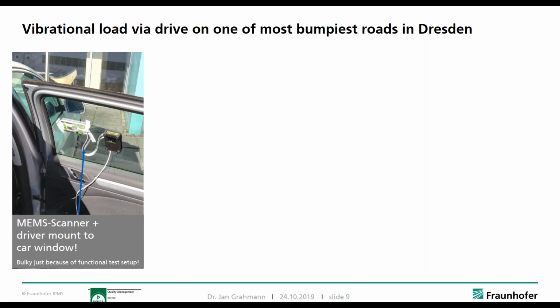For the resonant axis, that's different. For a resonant scanner, you basically have an approximately sinusoidal motion, which you cannot compensate. Each sinusoidal trajectory has a certain linear part, but it is of course smaller than what we can do with a quasi-static scanner. If you want to use a resonance scanner and you need a linear trajectory, then you have to stick to the linear part the sinusoidal trajectory gives you.